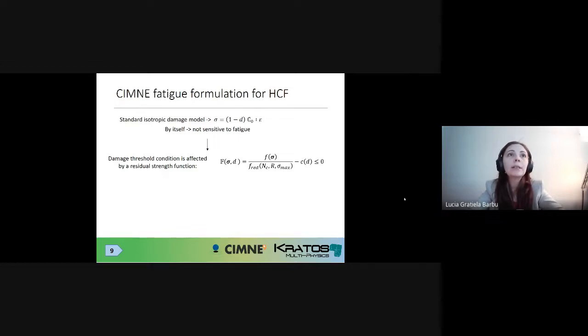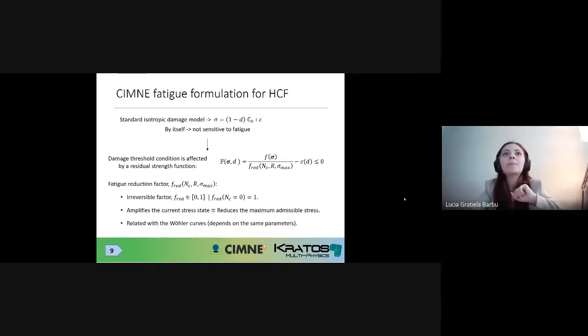So we have decided to affect the damage threshold condition by a residual strength function, which progressively lowers the strength of the material as you apply cycles, based on specific parameters, such as, of course, the number of cycles applied, the reversion factor of each specific stress state at each integration point, and also the maximum level of stress at each integration point.